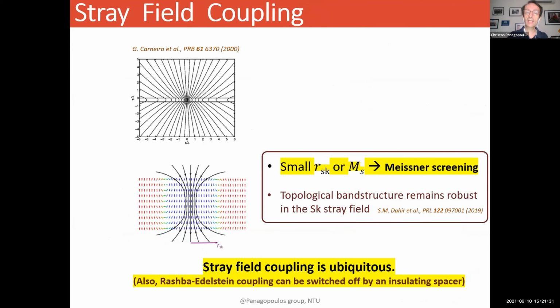A small magnetic skyrmion or magnetic vortex, or a small saturation magnetization in your magnet, would allow for Meissner screening. And a topological band structure would remain robust in the skyrmion stray field. So the stray field coupling would be ubiquitous. And exchange coupling can in fact be switched off, therefore, by an insulating spacer between your superconductor and your ferromagnet.